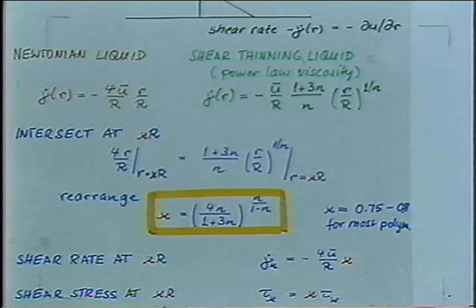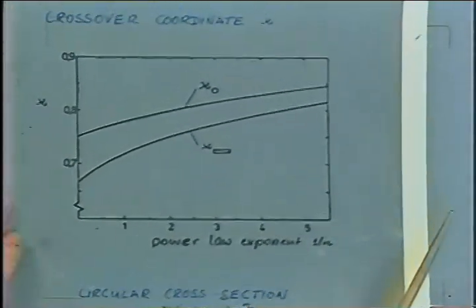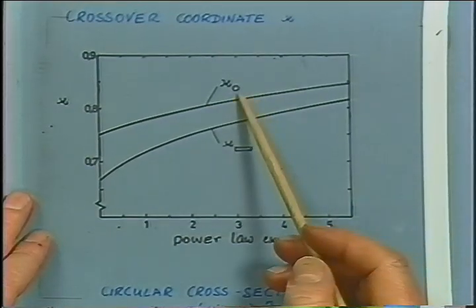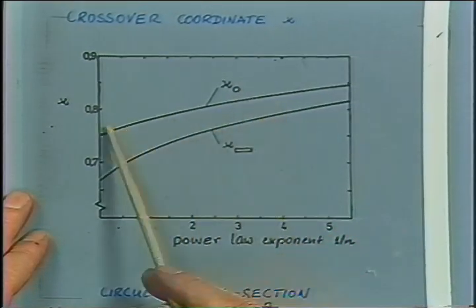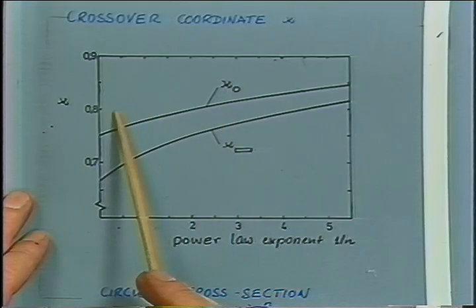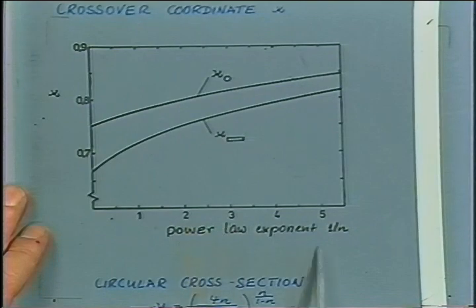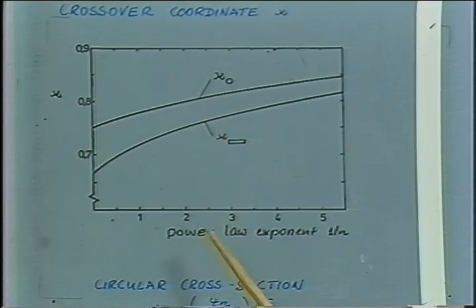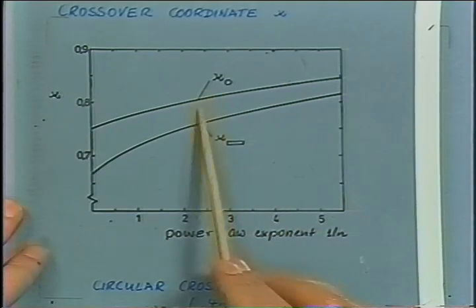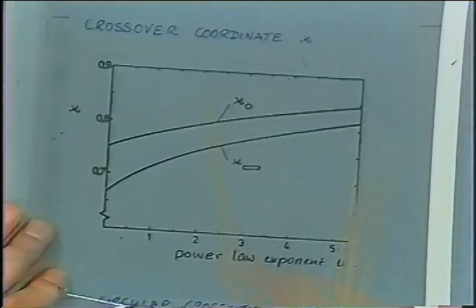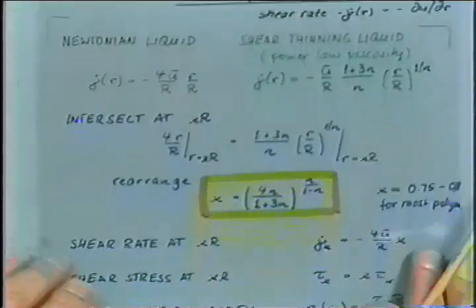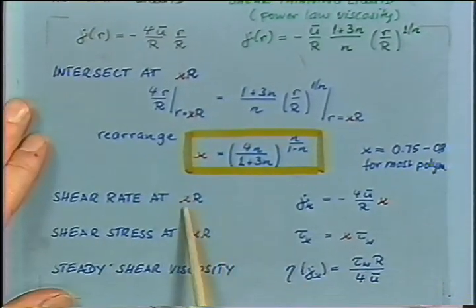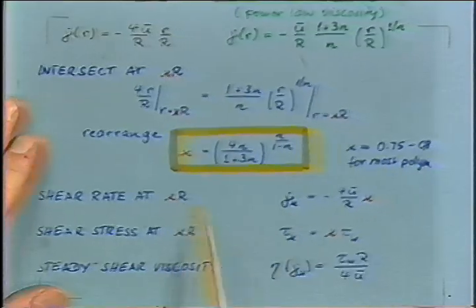Now, I plotted this function for various power law liquids, and you can see that, say, for a capillary of circular cross-section, this value, kappa, is about 0.8, pretty much independent of the power law exponent. So if you have a liquid, say, with a power law exponent between 0.6 and 0.7, you would not know it exactly, but you still would have a pretty good guess for kappa. And then you would use that kappa value and calculate the shear rate. Now, the shear rate at that radial position, kappa r, is given as the shear rate here from the Newtonian liquid.